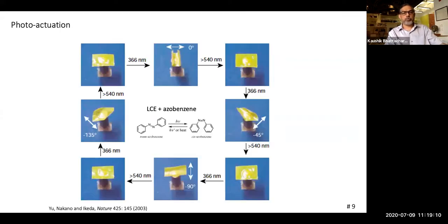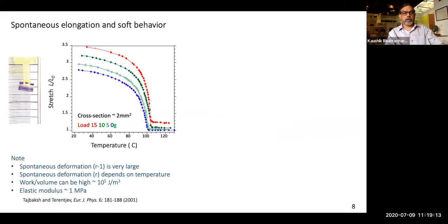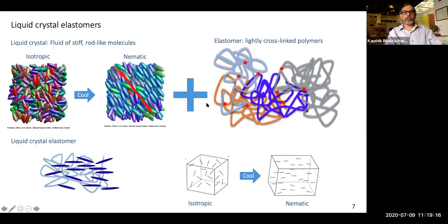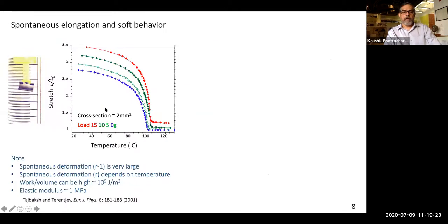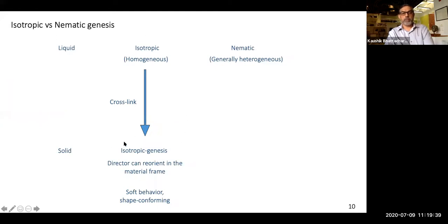But one more piece of material science before I move on. And that is, I told you that these materials were made by a combination of liquid crystals and elastomers, by cross-linking polymer chains with liquid crystal mesogens. And so I have a choice at what temperature I'm going to cross-link my material. So I start off with the liquid. It's isotropic at high temperature, nematic at a low temperature. If I cross-link it in the isotropic state, I end up with what I call an isotropic genesis material.